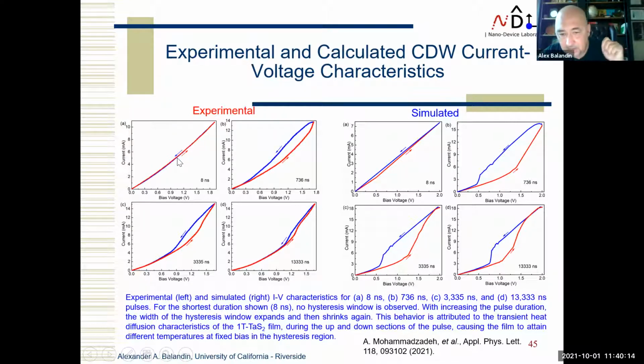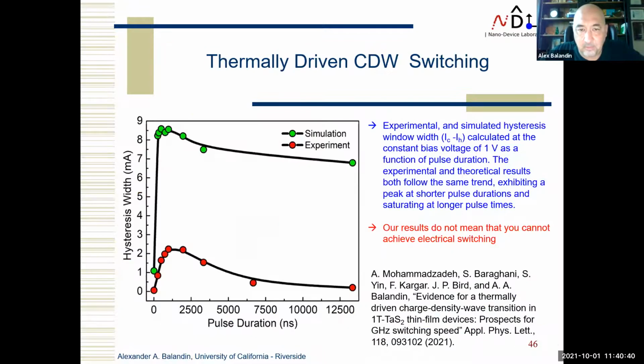When you start with very short pulses of the same amplitude, it does not produce heating. That's why you don't open the hysteresis. But once you increase the pulse length, you see the hysteresis starts to open. So this is experimental data. This is simulated. We simulated electron and thermal transport simultaneously using COMSOL. So the model was validated. You can see this is hysteresis width, this is simulation, and this is experiment. The trend is the same. The fact that they differ in height is not that important because we characterize hysteresis just by the difference in opening and closing voltage.